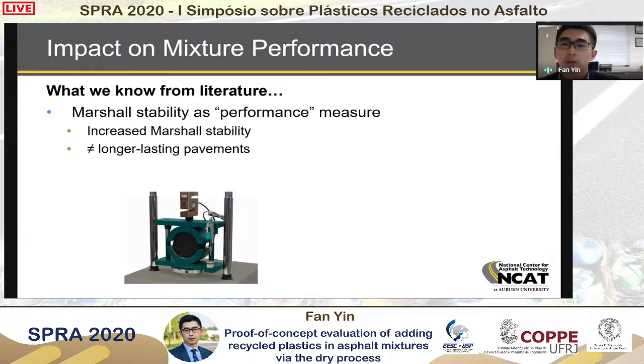So what happened to the mixture when we add the plastic into the mix using this dry process? By doing the literature review, we found that many researchers use Marshall stability as the measurement of pavement performance. And those studies consistently show the conclusion that adding recycled plastic can increase the Marshall stability. Based on this observation, some researchers indicated that, because of the increased Marshall stability, adding recycled plastic can provide us with longer lasting pavements.